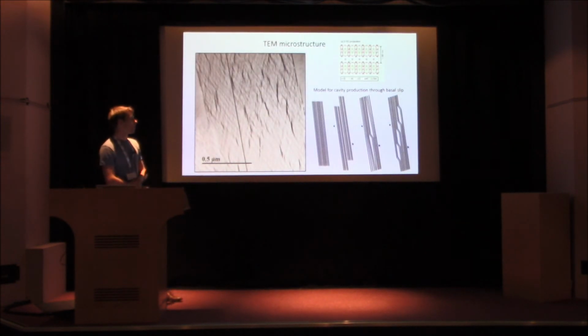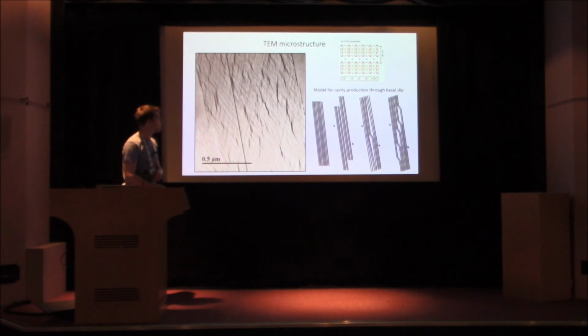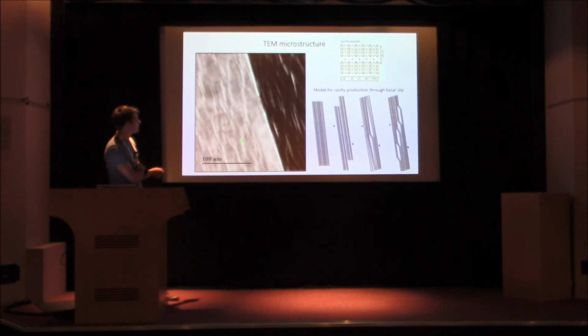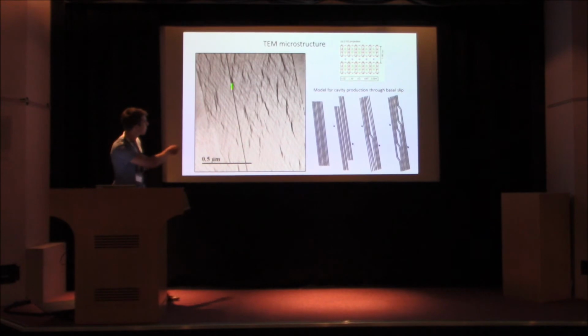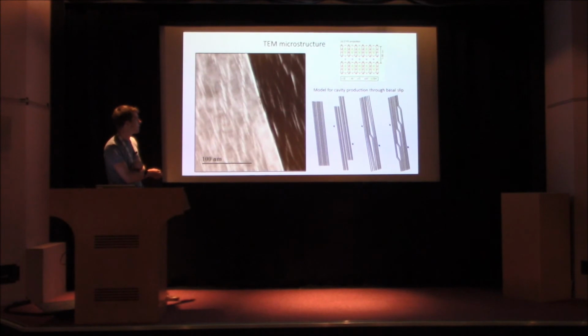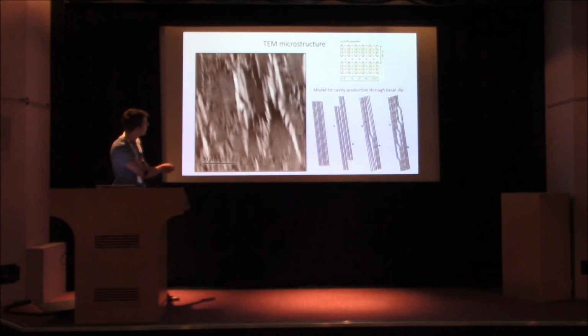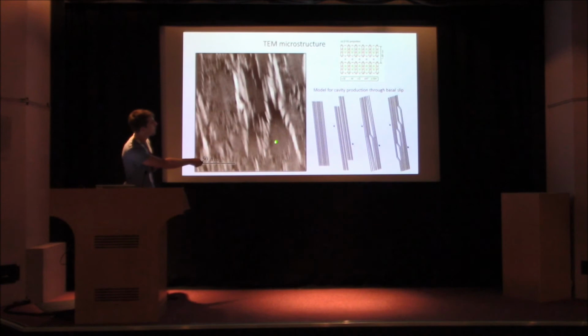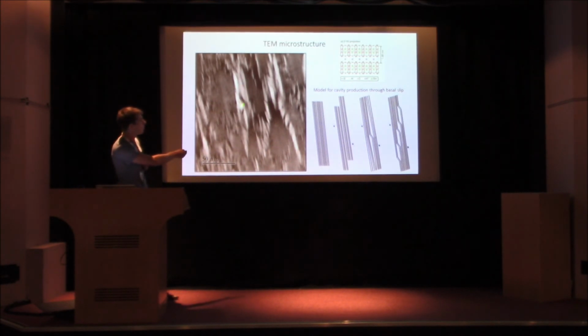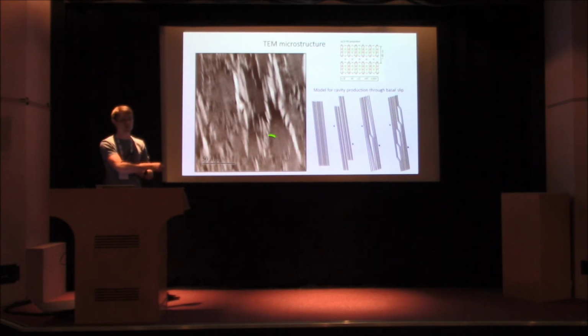If we look down to some high resolution, this is TEM imaging now, transmission electron microscopy. So you can get down to some really fine resolution. It's actually quite amazing, because these stripes in here are on an atomic scale. They're these layers in the crystal structure I showed you earlier. These strands here are actual atomic layers, and you can see voids opening up and this damage within the mineral structure. So this is an example of internal crystalline damage.